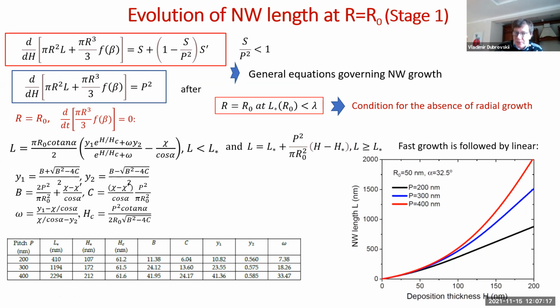on a sticky substrate. So basically what we see if we plot nanowire lengths against deposition thickness, at a fixed radius of 50 nanometers and for a given beam angle of 32.5 degrees, is that the curves increase fast in the beginning. But then, after you reach the shadowing length at a given radius, they become linear in time. And even here at the beginning, the increase is more complex than exponential.